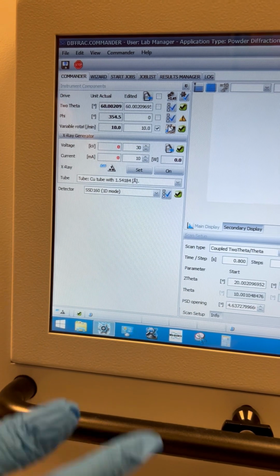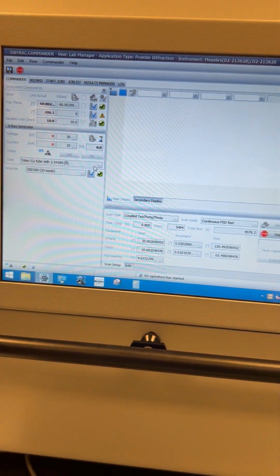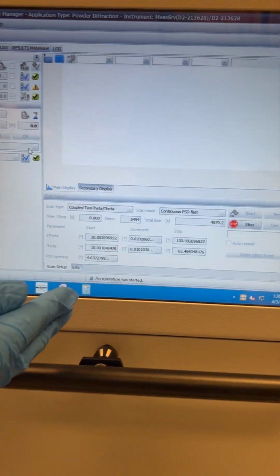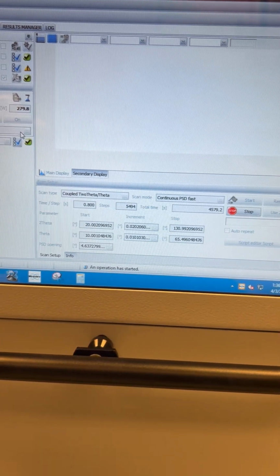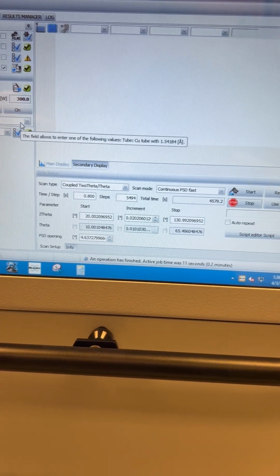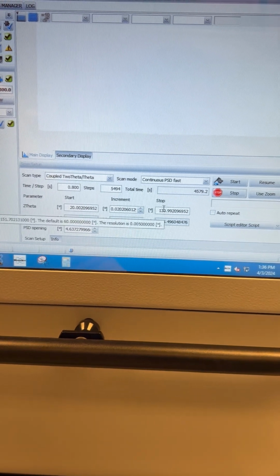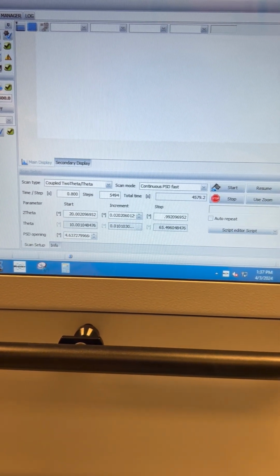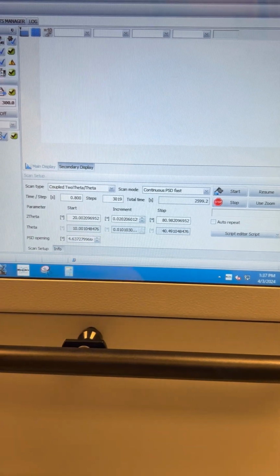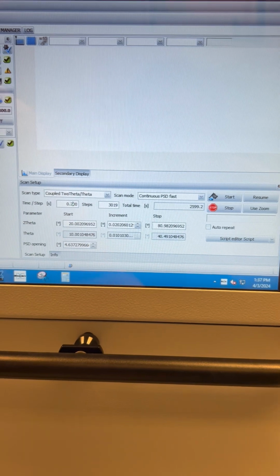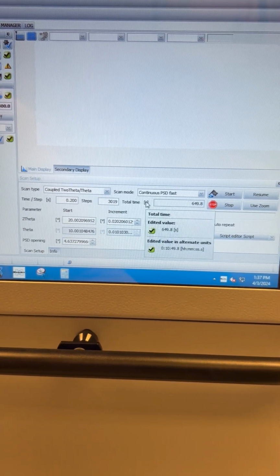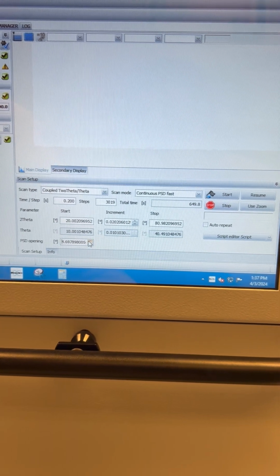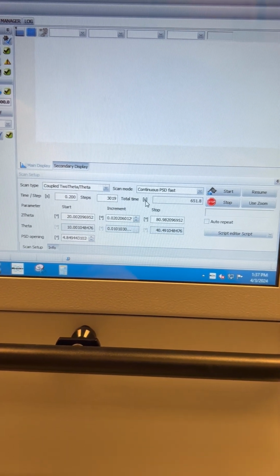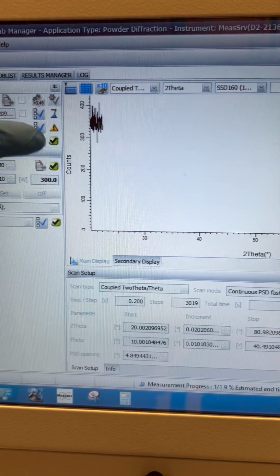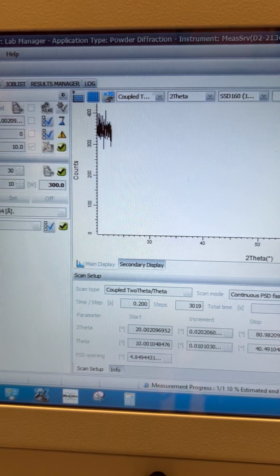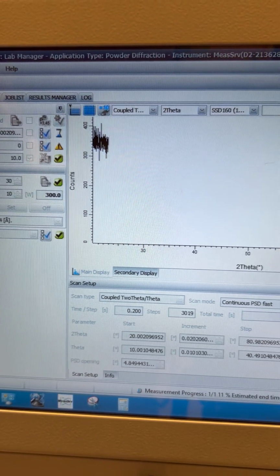If you look very closely, you can see that the value for phi is changing, which means that the sample is rotating. And now that the x-rays are turned on, I can go ahead and input my specified values with which the sample will be run. The values that were input were used consistently for samples 2 and 6 since 4 was omitted. Here we used a 2 theta data range of 20 to 80 with an increment of 0.02, a time per step of 0.2, and the PSD opening was set to a maximum.